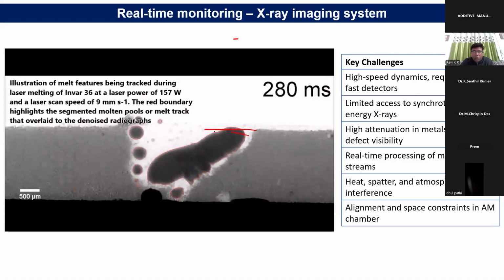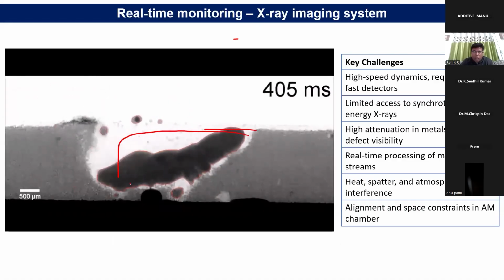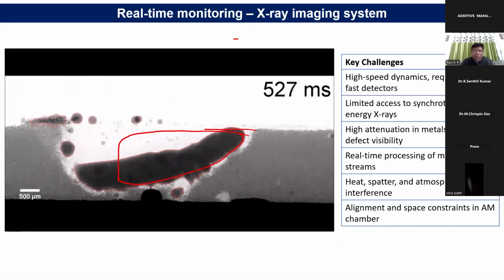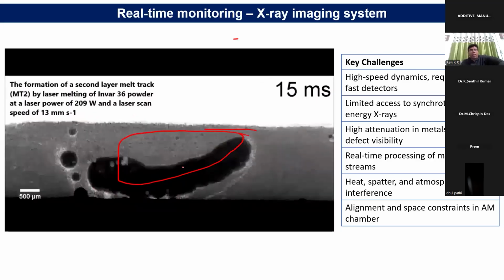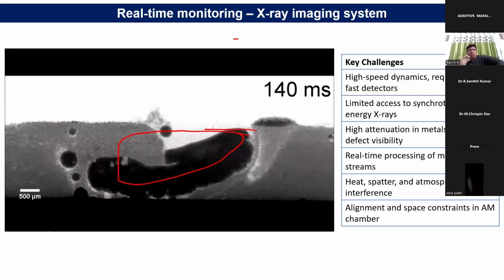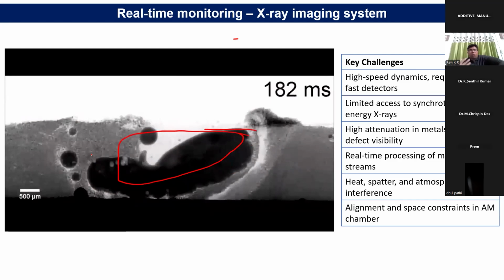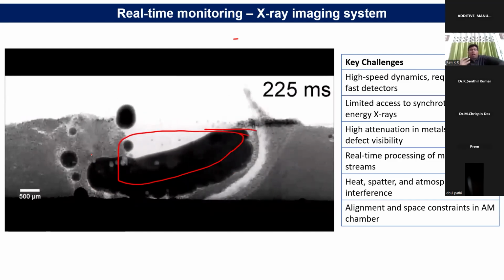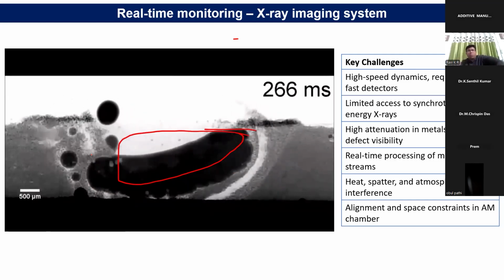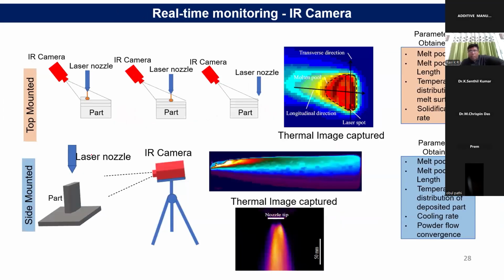I need to understand what happens on this subsurface. This particular technique will give you an idea about the defects which are forming, and this understanding is very important. This can be done using X-ray imaging, but this technique will give you only an idea about how the defect forms. You cannot actually use it to control the defects. You can see here, all this information one can very nicely get.